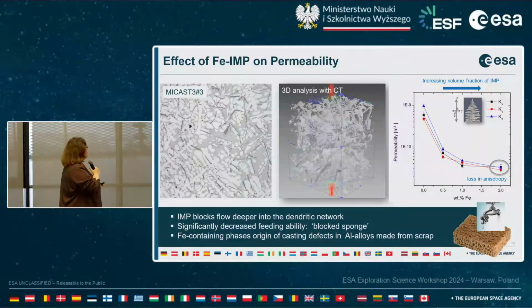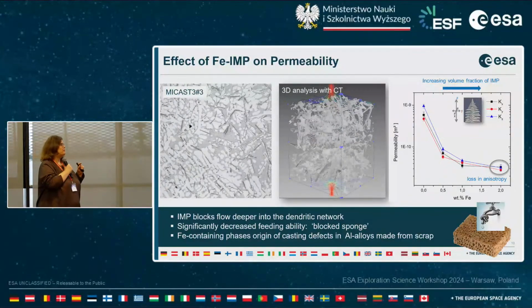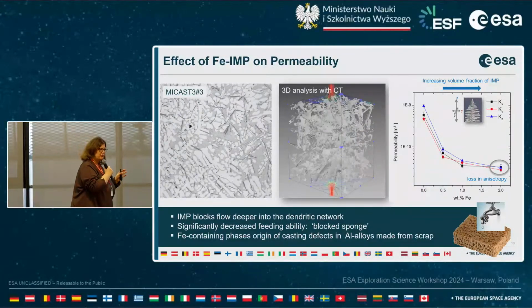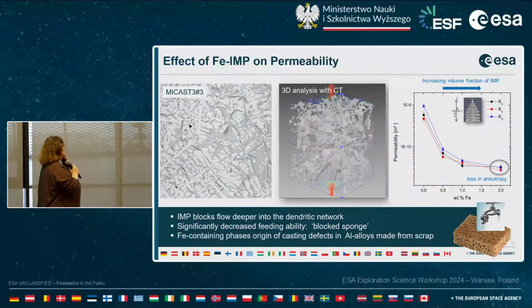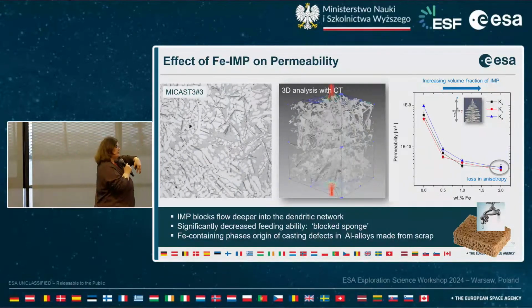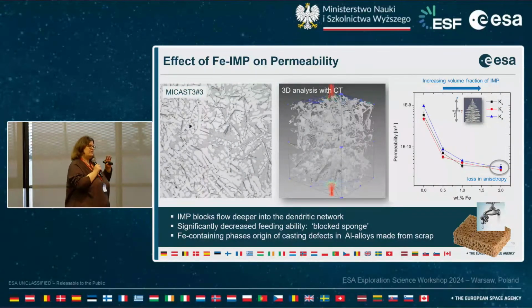And what we found is that the intermetallic phases are definitely not needles, they are platelets. Very long platelets, but very thin. The thickness is around 2, 3, 4 microns, but the length can be 600 microns, so in principle filling the room between two dendrites. This is the picture you should have in mind: these intermetallic phases block the flow deeper into the dendritic network, and on the other side, of course, they are consuming the solute rejected from maybe disappearing side arms. It's a double effect, but the biggest effect is, of course, the presence of the intermetallic phases.